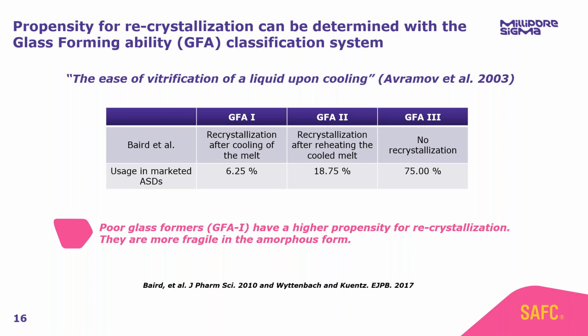And then finally, we have the so-called poor glass former molecules, or GFA class 1. These are molecules that when you melt them down to remove the crystallinity, as soon as you start to solidify, as soon as you start to cool down, that molecule will crystallize. This is sometimes known as cold crystallization. And that means that even as you are proactively reducing the energy in the system, there is still an energetic driver to recrystallize. That means that these molecules are not stable in the amorphous form. They have an incredibly high propensity to recrystallize, and as a result, can be really challenging to formulate with polymeric amorphous solid dispersions. It's no surprise then, if we look at the data below from Wyttenbach and Kuentz, that the distribution of commercially available amorphous solid dispersions is weighted heavily towards good glass formers.